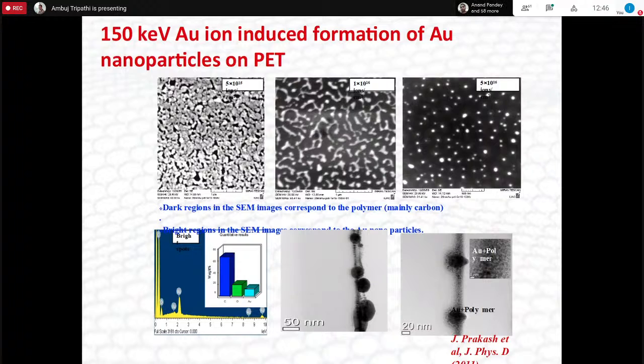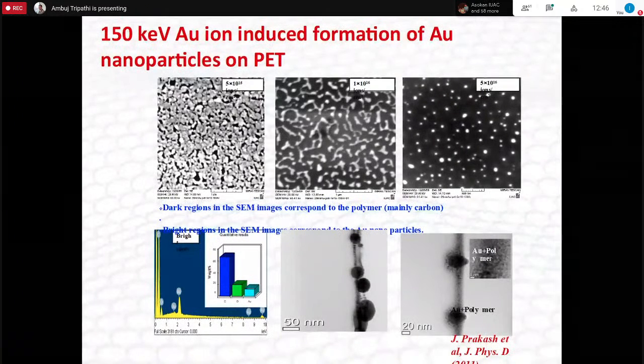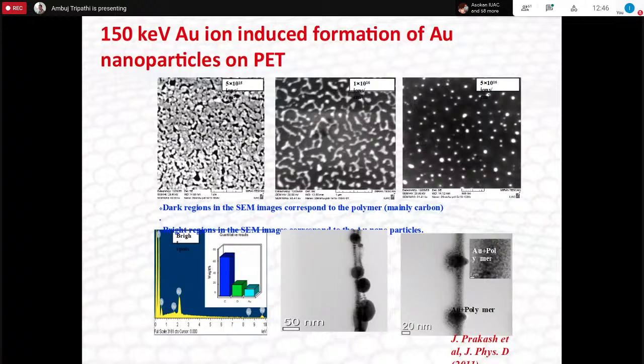So this was a gold thin layer, and then with irradiation, you can make these nanoparticles. On the lower side, this central image is the TEM, where you can see the circular nanoparticles. And as you increase the fluence, in the last image at the bottom right, you will see that they are getting elongated. So you can also do the shape engineering. You can make nanoparticles on the surface, and you can also do it embedded.